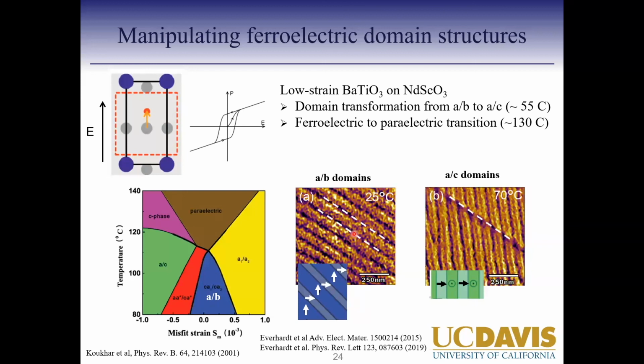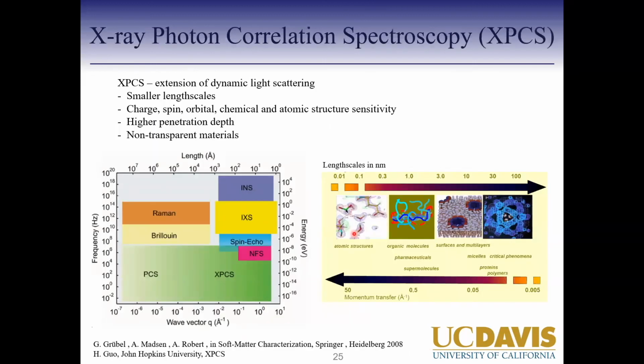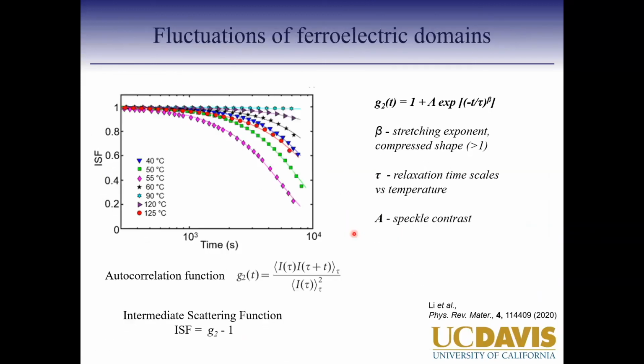And then another question. You mentioned this stretched exponential exponent shows up everywhere. Is there a range to the exponent that shows up, or is there some value that they all fall on for some reason? So typically it's around 1.5. If we were able to capture the full decay, then I would be able to put better error bars on it. But the error sometimes is 1.5 plus or minus 0.2 or so.